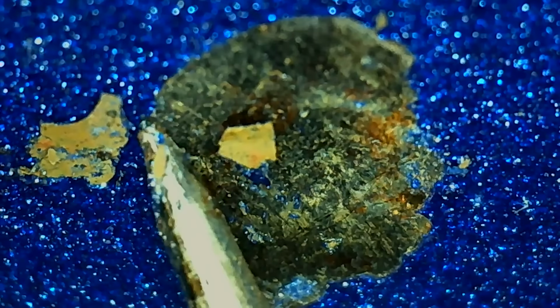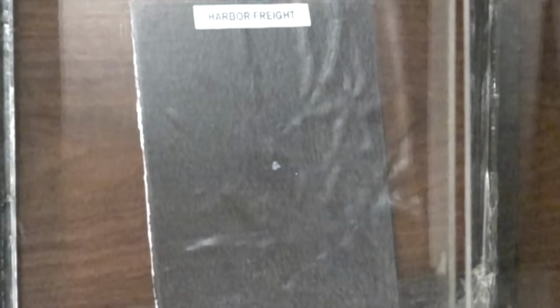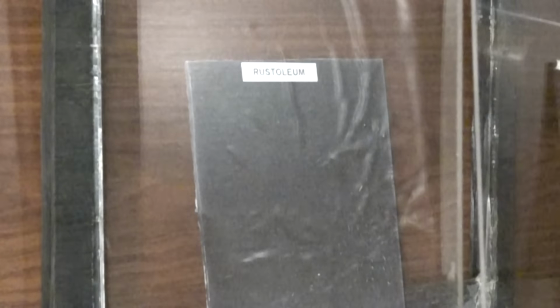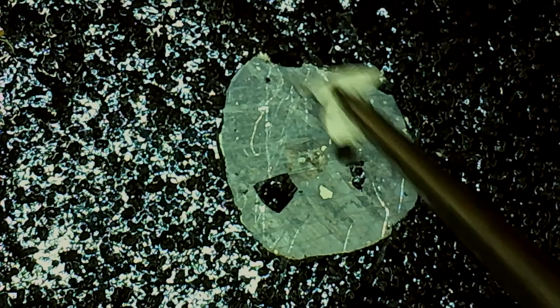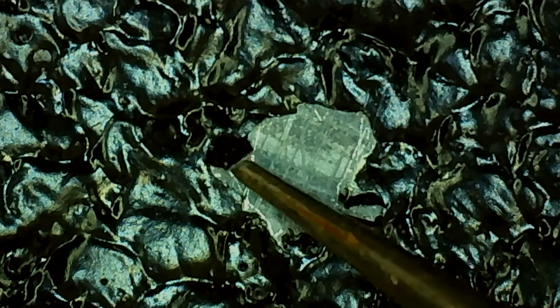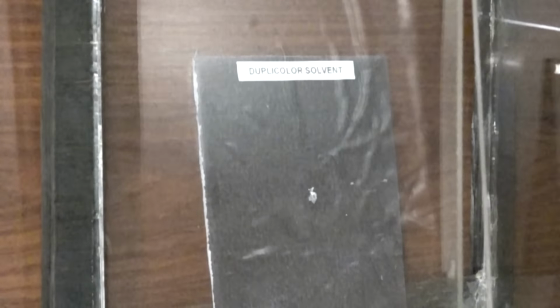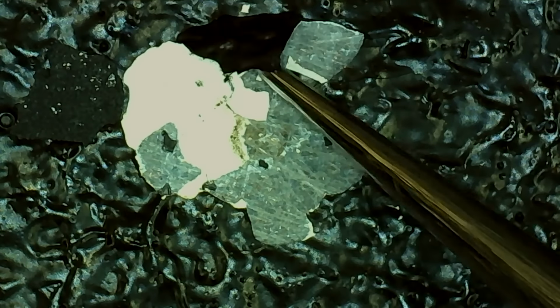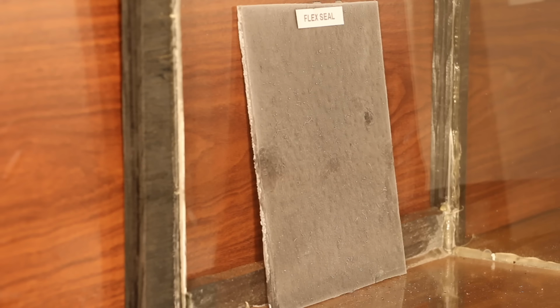The size of the damaged area of the spray-canned metal was 6.5 millimeters. The size of the damaged area with the Harbor Freight Iron Armor was 9.09 millimeters. Rust-Oleum performed a little bit better than Iron Armor with a damaged area nearly a millimeter smaller at 8.15 millimeters. EGC did the best yet at 6.16 millimeters. The oil-based Dupli-Color really struggled at 13.61 millimeters.